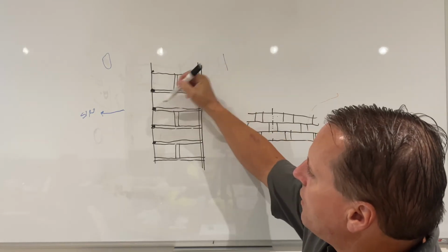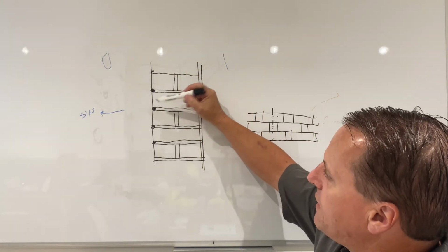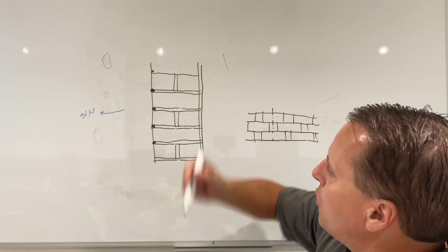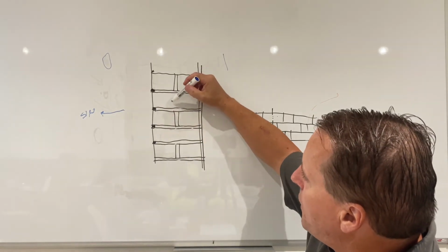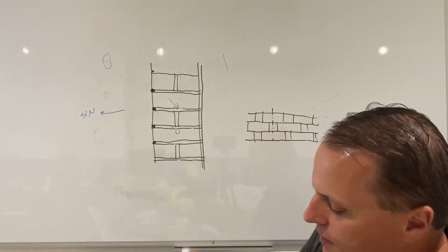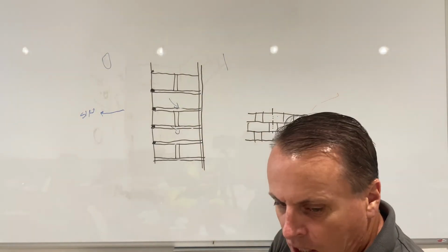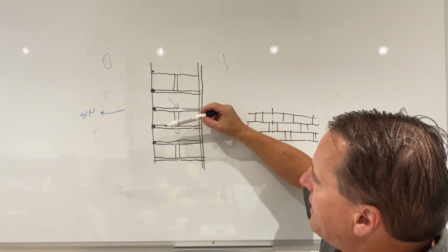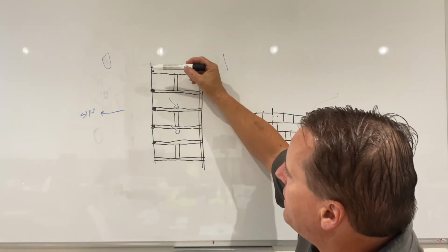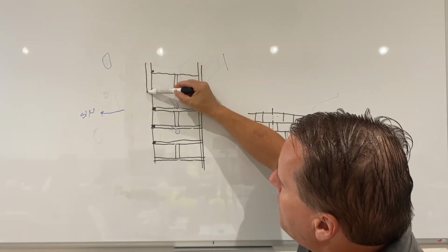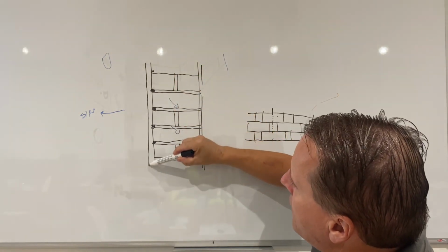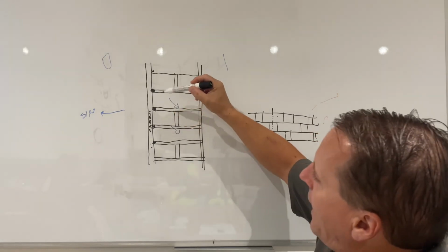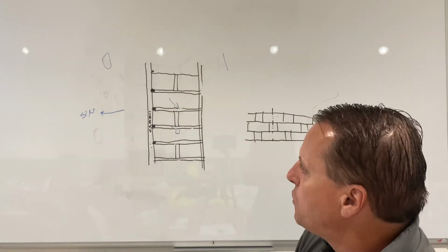And because water can't evaporate out the face of that anymore, the brick faces start to spall. The other issue is, because the face of the wall is less moisture vapor permeable, more moisture comes through to the inside of the property. So what I suspect has happened here is they've repointed and the issues continued. So what they've then done is they then put a cement render on the front of the building, and this is cement, thinking that'll stop it, that'll stop any rainwater getting in.